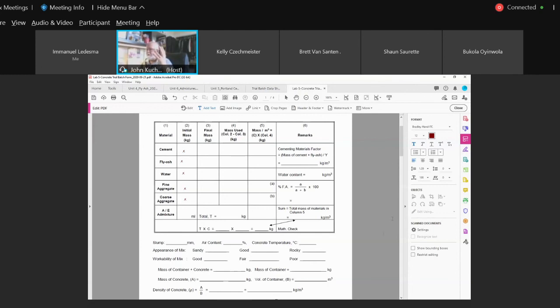I can't remember what table number it is, but if you have some time, go through all those tables. There's a section that tells you the least thickness of your structure and what the concrete temperature should be. That's because if it's too thick, you want lesser temperatures due to heat of hydration and thermal expansion. So for a 150 millimeter barrier curb, the temperature within that can be higher than if you're using a structure that is 5 times as wide, 5 times as high, and so on.